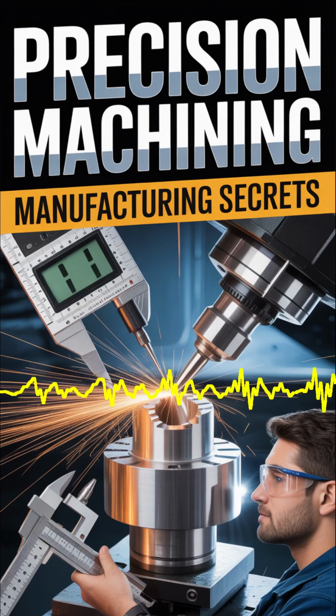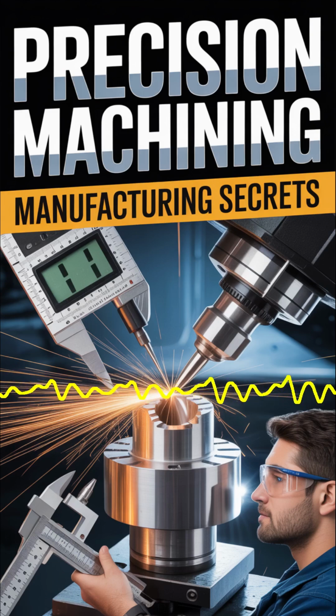Now that's the simple version. The sources mention a modified equation that adds in feed and depth of cut, but it still holds that the velocity exponent is the biggest. Why is velocity so much more destructive than, say, just taking a deeper cut? Because velocity is what drives heat generation. The faster you go, the more friction, and the temperature at the cutting zone just rises exponentially. And since we know diffusion and deformation are driven by temperature, speed just accelerates failure way faster than taking a deeper cut, which mostly just increases the mechanical force.